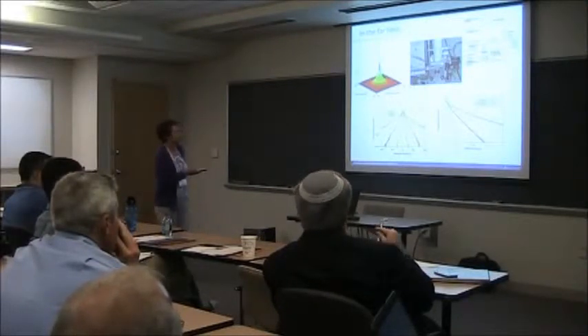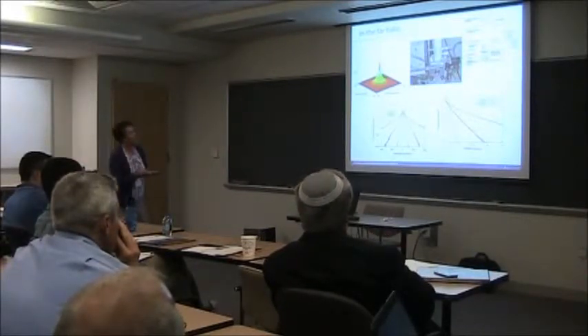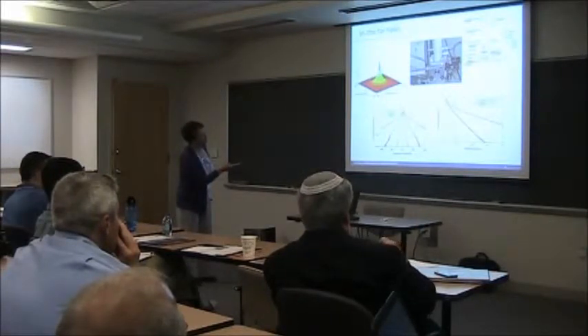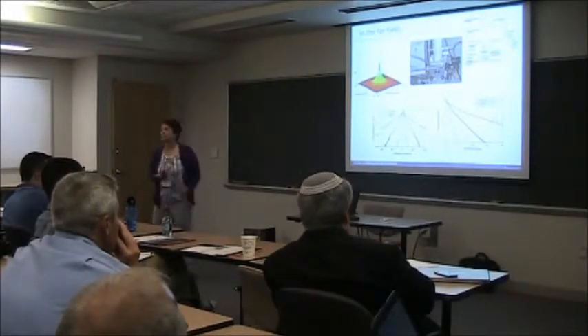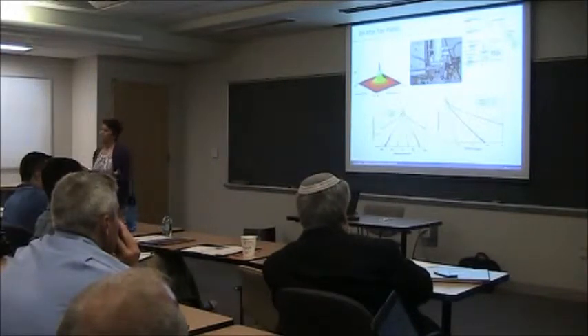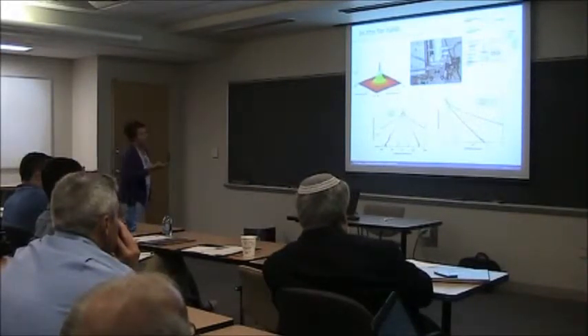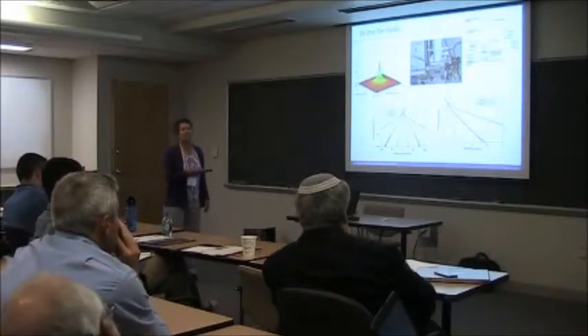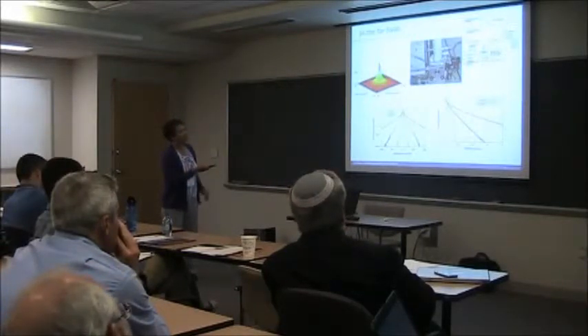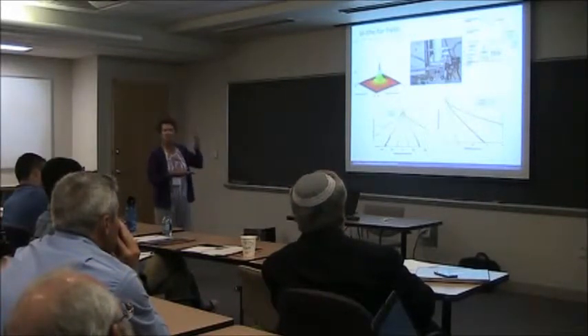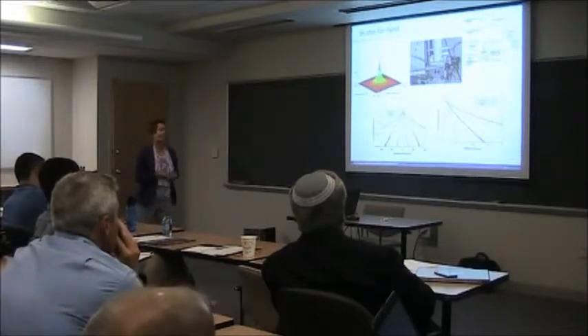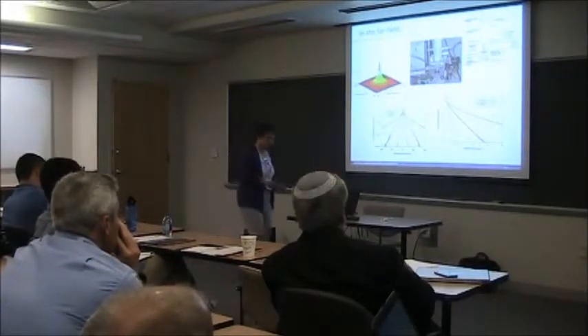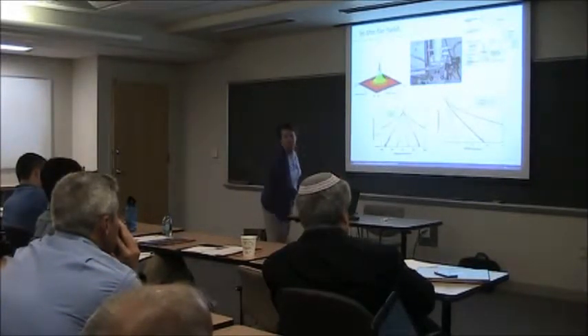So here's the data for 3 different materials on a log scale, as a function of distance. The black are the data points. The solid lines are the Bessel function fits for diffusion from a point source. And as you can see, you can get really high quality fits and therefore extract, with one image, minority carrier diffusion lengths, which are very important for people that make a lot of devices and of course in particular solar cells.